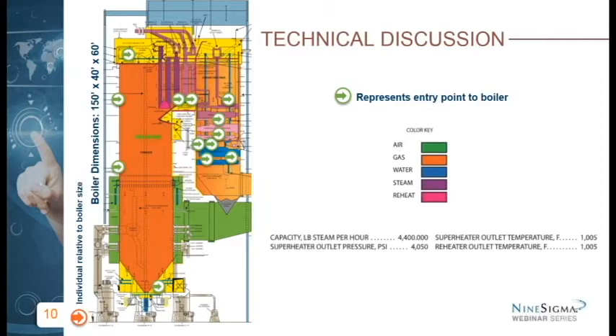So what happens in the purpose of the challenge is that as we burn either coal or gas, and it's usually more of a coal problem, these walls erode. Coal is fairly abrasive, and then as it burns, it turns into ash, which is also abrasive. But with natural gas as well, we can also have a corrosion issue in certain areas, depending on how we manage our water chemistry and a number of other factors.